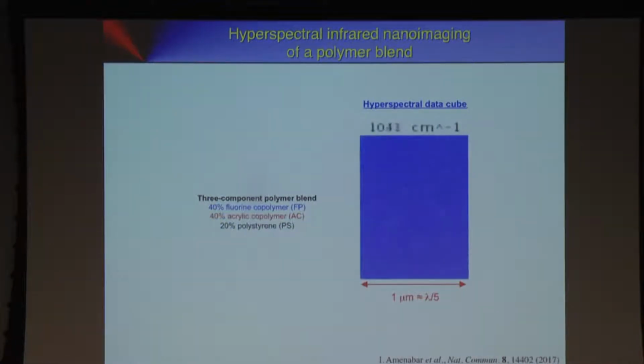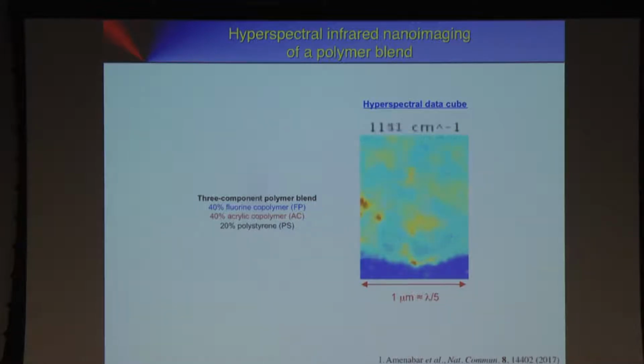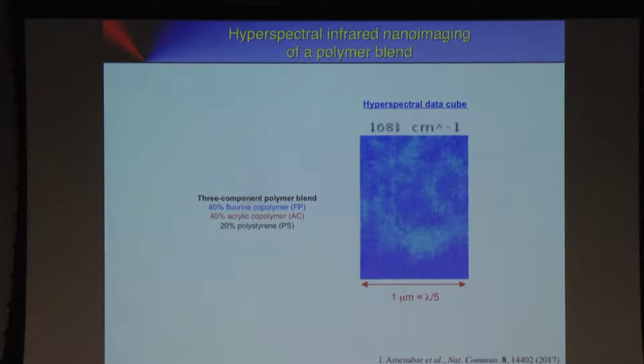So this is how it looks if we go through this data cube in frequency. So now we slice through. And you can see that the signal to noise is already pretty okay to get some meaningful information out of that. So the sample that we looked at here was actually a 3-component polymer blend. It was 40% fluorine copolymer, 40% of acrylic copolymer, and 20% of polystyrene. And the image contrasts are already rather complicated.